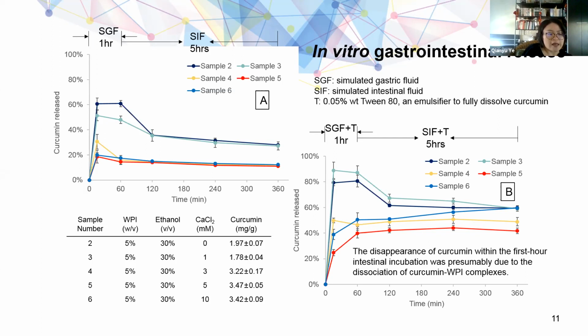0.05% Tween 80 as an emulsifier to fully dissolve curcumin was added into the simulated GI tract. In Figure B, we can see that their overall release trends were similar to those without Tween 80, and the corresponding curcumin contents detected were comparatively larger. This is presumably due to the dissociation of curcumin WPI complexes with the enzymatic hydrolysis as a function of time and the resulting formation of free curcumin released.